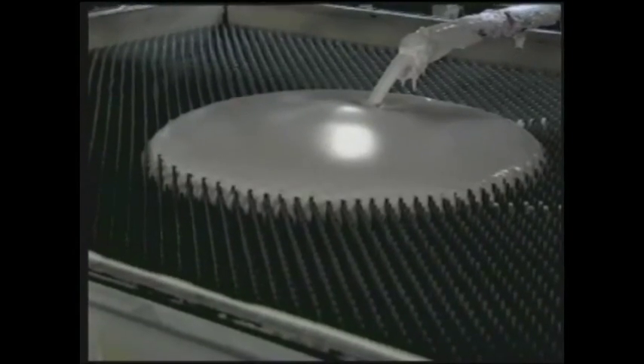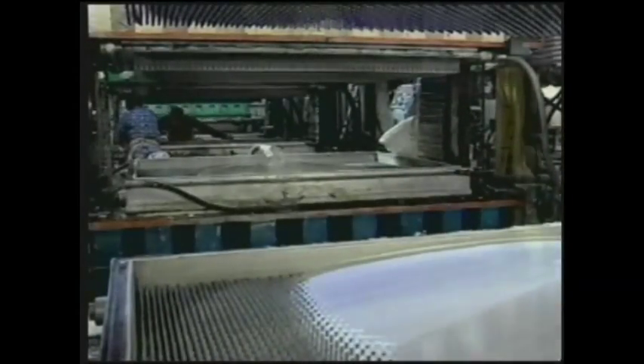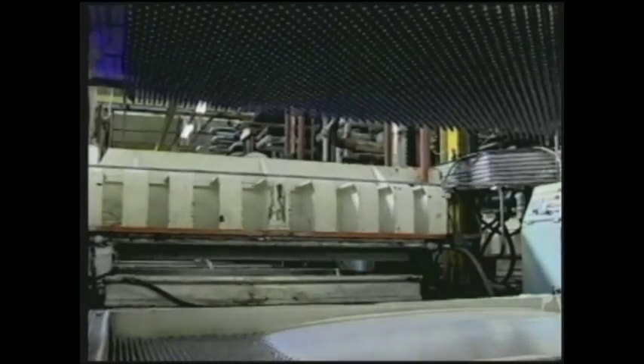The liquid is then continuously frothed by mixing with air in a foaming machine, from where it's poured into a large fixed mould to only partially fill it. The lid is sealed, and the latex is expanded by vacuum to completely fill the mould. As the latex fills the mould, the bubbles in the uniform cell structure are stretched until they are interconnecting.